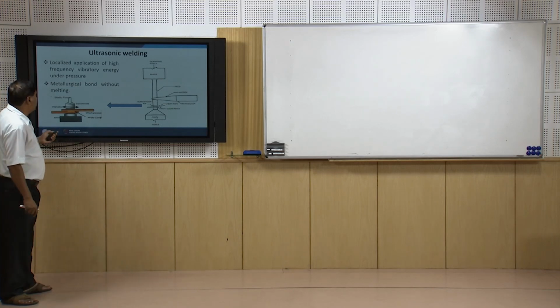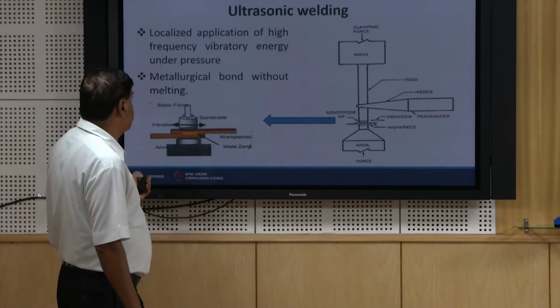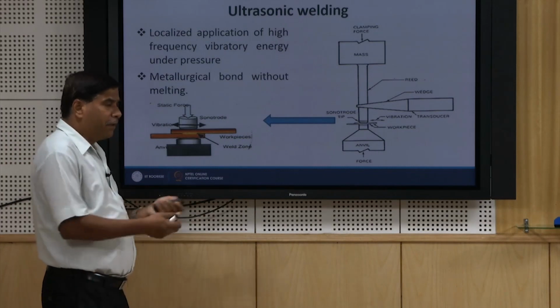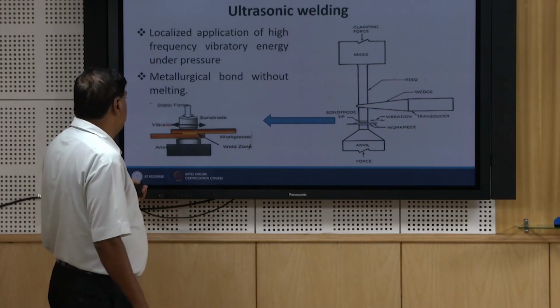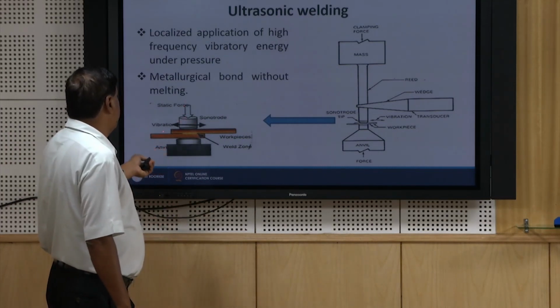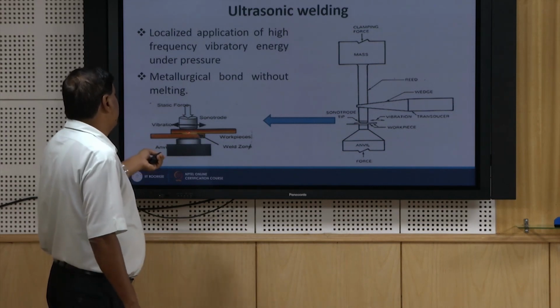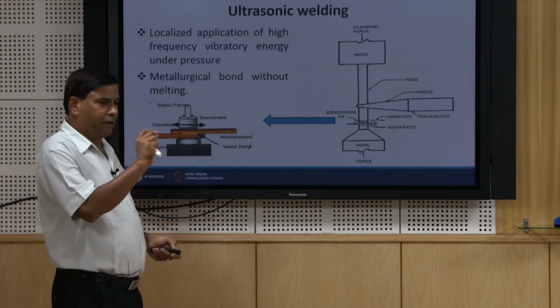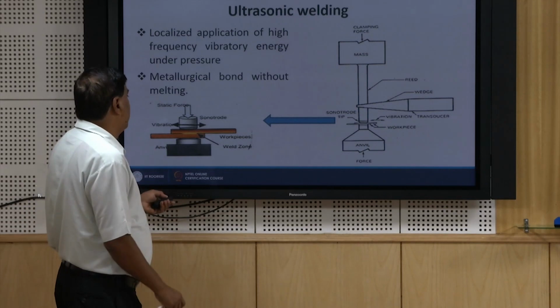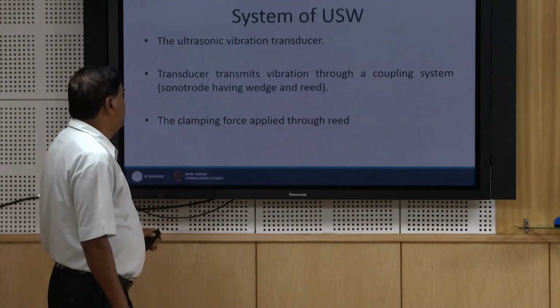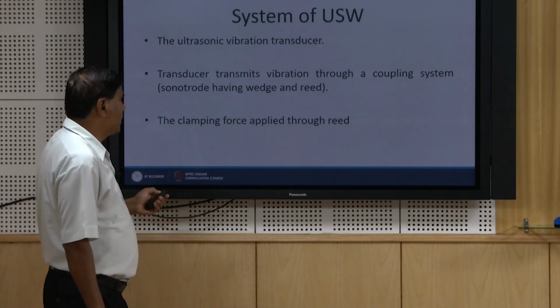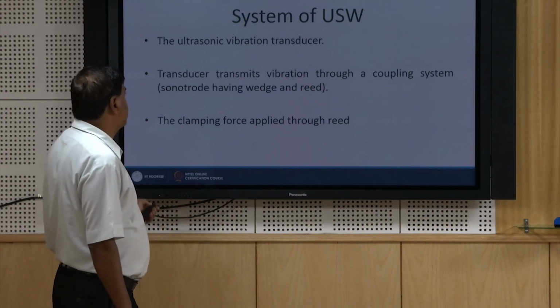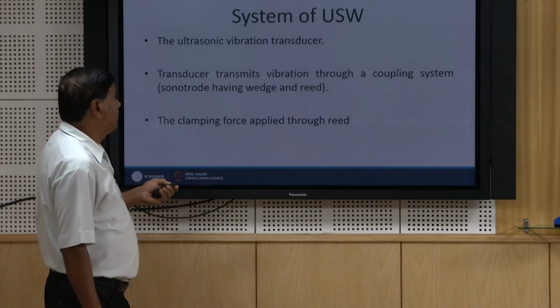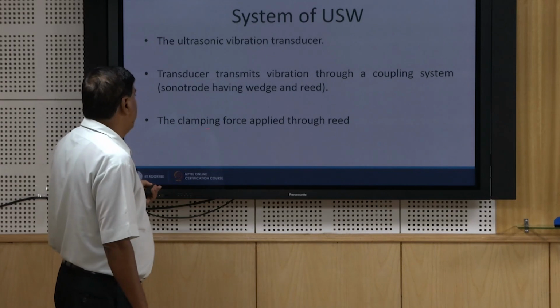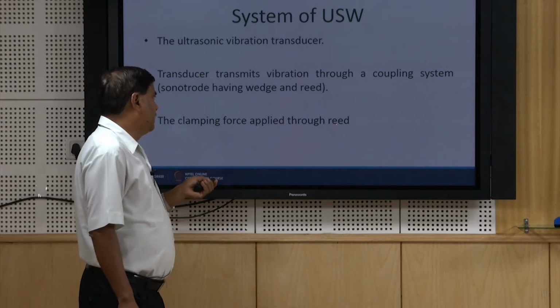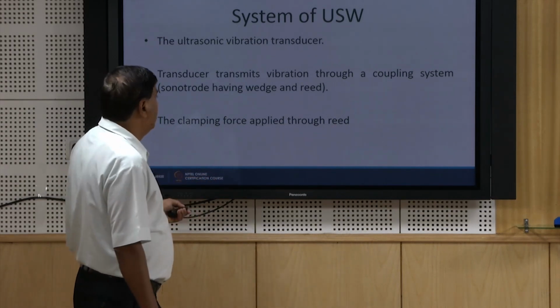The very localized application of high frequency vibratory energy under pressure creates a metallurgical bond at the interface. This is the sonotrode tip; static force and vibratory energy facilitate the deformation at the interface, and that helps in the development of the weld joint. Ultrasonic vibrations are transmitted through the transducers. The transducer transmits the vibrations through a coupling system, and clamping force is applied through the reed.